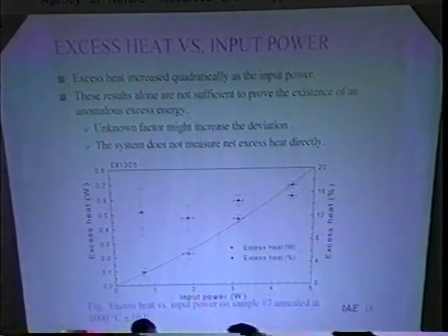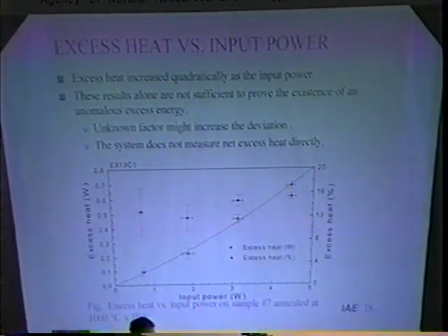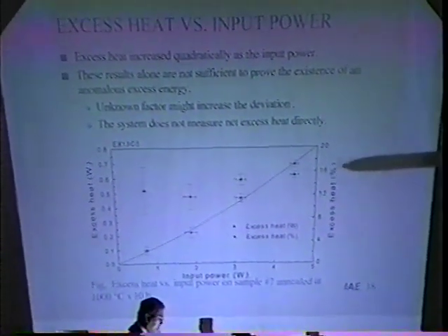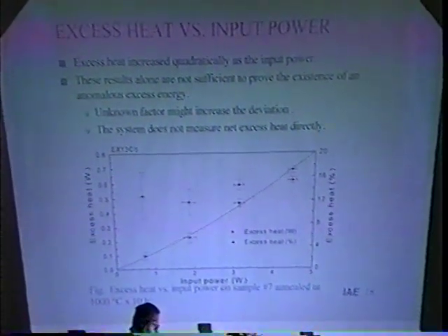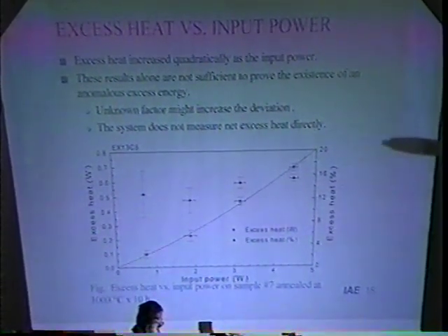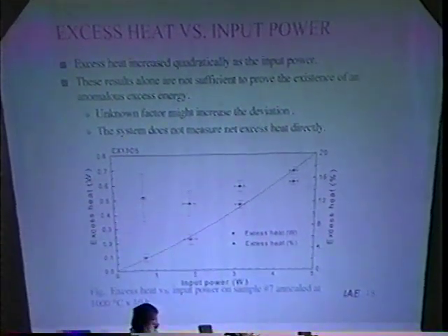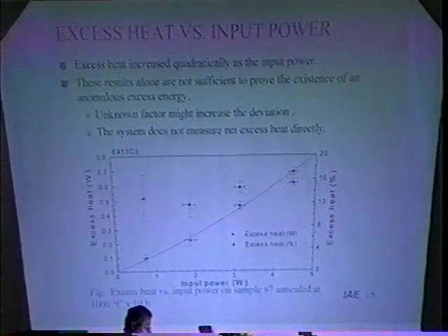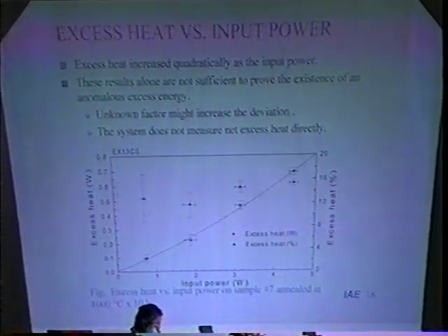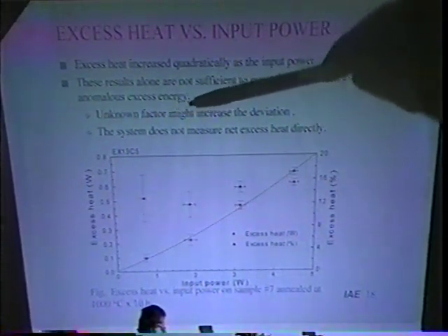This figure shows the typical relationship between input power and excess heat in our experiment. The solid line is a quadratic fit using the least square method. The excess heat increased quadratically as the input power corresponding to the surface current density increased. However, these results alone are not sufficient to prove the existence of an anomalous excess energy. Although we have estimated that the deviation from the calibration curve was less than 5%, as previously mentioned, we cannot rule out the possibility that some other unknown factor might increase the deviation from the calibration curve for the system.